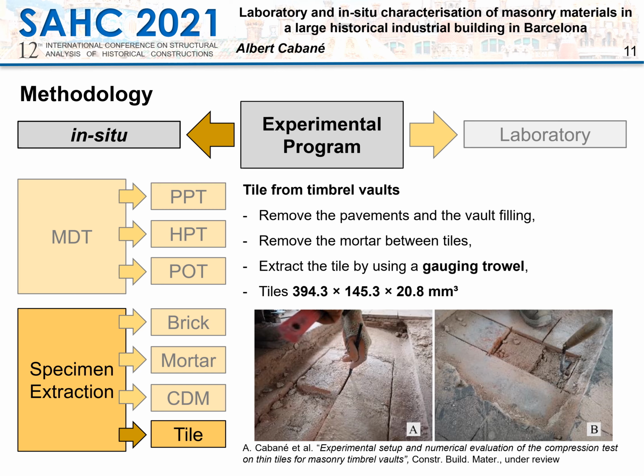Extraction of their components has been done from the top of the timbrel vault. A thin chisel was used to remove all the lime mortar joints around the tile to be extracted, and then a trapezoidal trowel was slowly inserted under the tile and used as a lever. While levering the tile up, the trowel was lightly tapped with a nylon hammer, trying to avoid any crack appearance in the tiles.